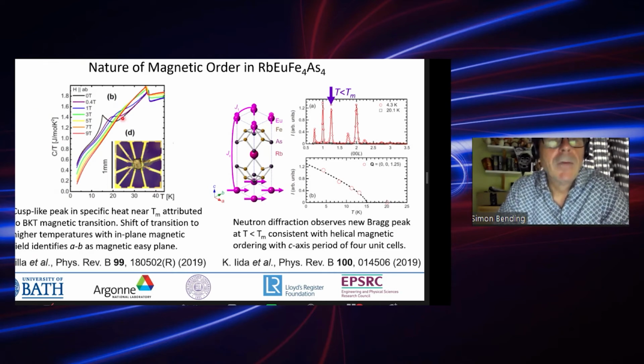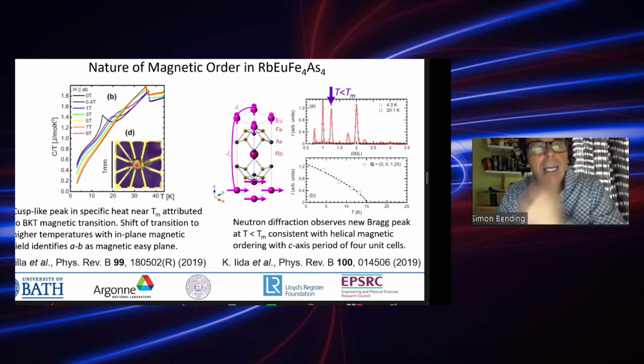And here we show data for the heat capacity in different in-plane fields along the AB plane. And you can see the characteristic trend is as you apply the field, this cusp washes out, but it actually shifts to higher temperatures. And that's a smoking gun for the fact that the easy axis is actually in plane. It's along somewhere in the AB plane for the moments, these spin-only moments lying on the europium atomic sites.